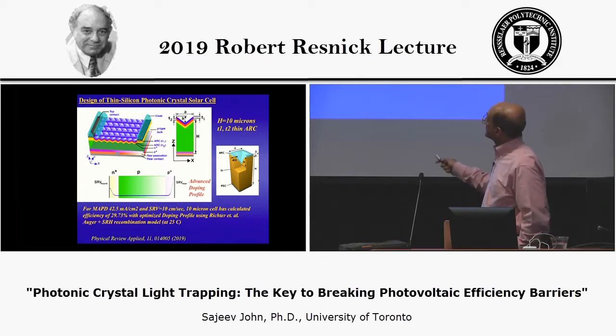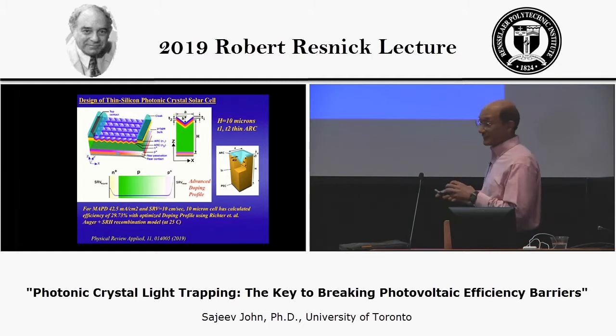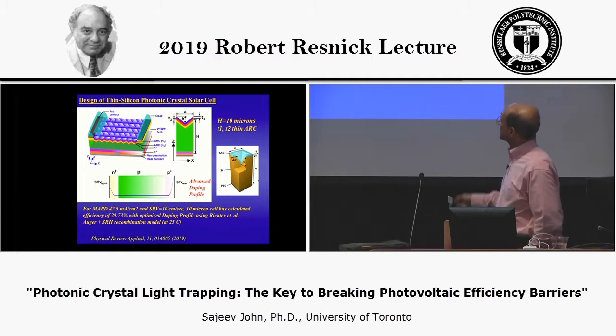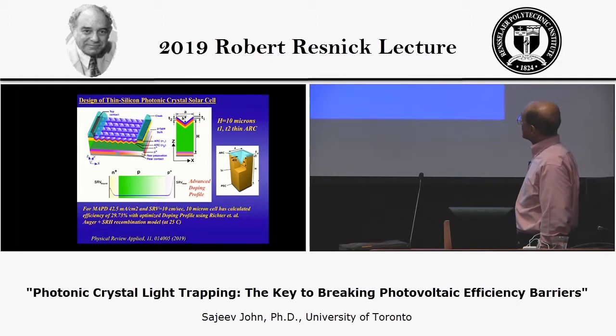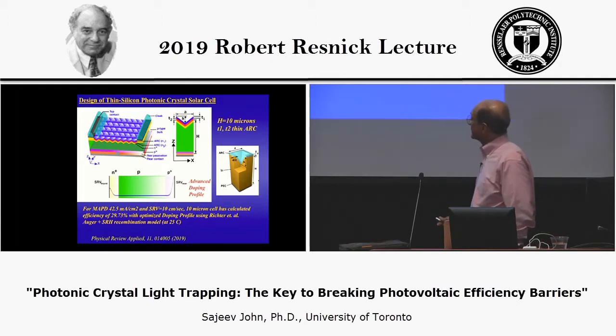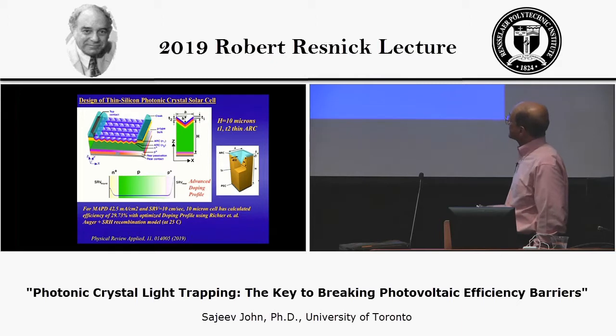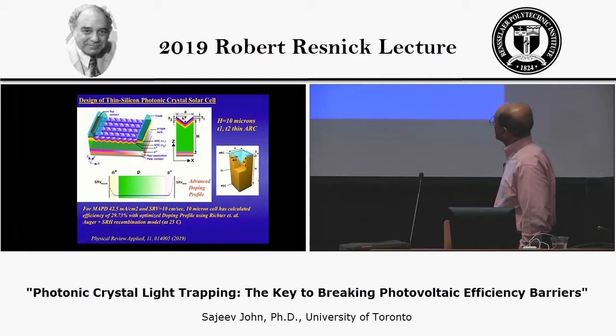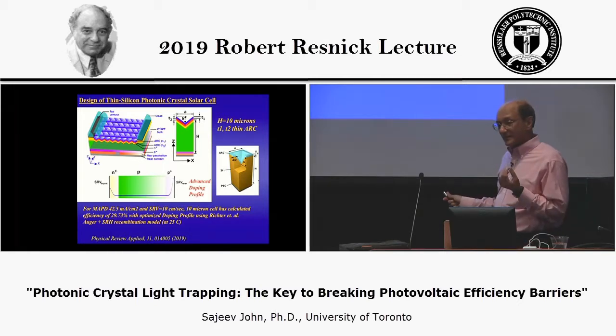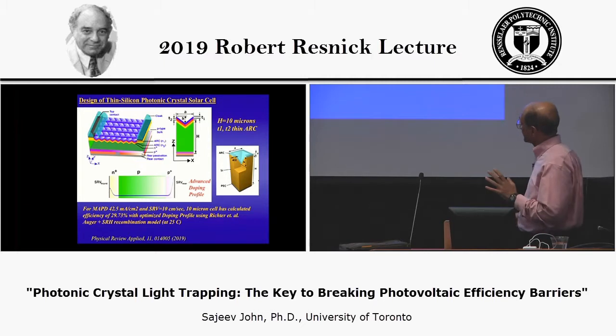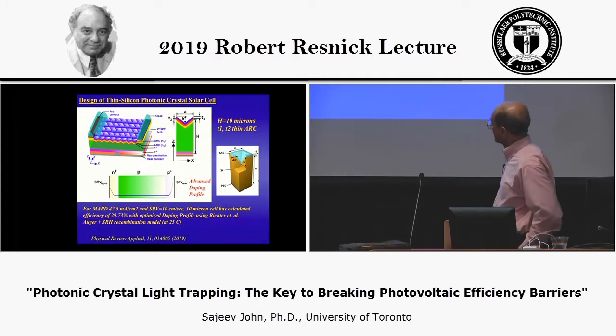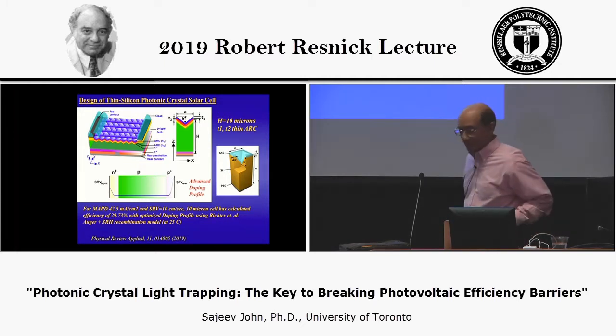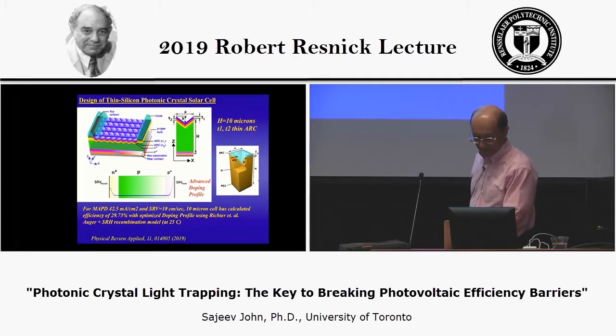And in this case, we also consider top contacts with some dielectric surrounding it to try and cloak as much of the contact to prevent shadowing loss due to their presence. And in this case, for an MAPD of 42.5 and a surface recombination velocity on the order of 10, this 10 micron cell, assuming absorption only from the 300 to 1100 nanometer range, had a computed efficiency at 25 degrees centigrade of 29.73%.